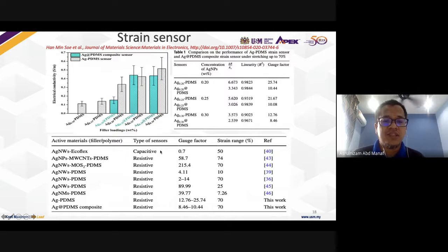At that time, with assistance from the School of Material's group, they did a lot of ink formulation, where the formulation depends on the percentage. There is a nanowire with PDMS, and that can act as a capacitor or insulator. So there is a mix with the PDMS, and that is the ratio. We changed from 0.1, 0.15, 0.2, 0.25, and then 0.3. That is the percentage of filler loading, to improve the conductivity.